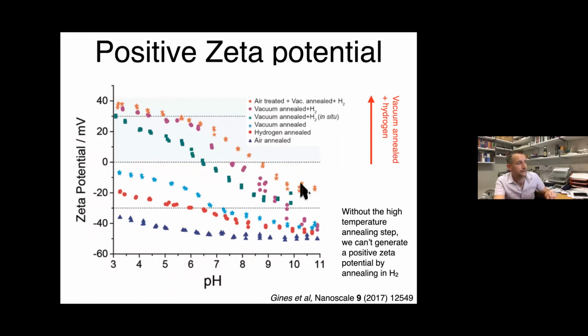And so what happens to the zeta potential? Well, if you don't do this annealing step, you can't create a positive zeta potential on these materials, on the larger grain size, right? Now, small caveat, some people have claimed with a hydrogen plasma you can, but we also did that back in Germany and never published it because we were convinced that it was actually graphitization because we saw a change in color in the particles, so we never actually said anything about it. In this case, if you do a remote hydrogen plasma, it doesn't go positive. So if you try and remove the plasma contact from the sample, I don't see it going positive. I see it going neutral, which is what I expect actually.